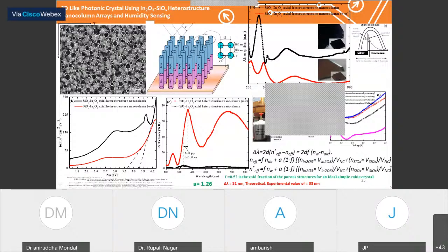We have seen that as the humidity has been enhanced inside the chamber, the current conduction of the devices has been enhanced. We have used some theoretical approach to determine the change of the band gap. We have seen the change of the band gap for both cases, theoretical and experimental, is nearly equal, and just 31 nanometer and 33 nanometer have been calculated, and the change of the conductivity has been measured for up to 99% humidity, changed from 55% humidity in the materials, and this has been due to the absorption of water at the junctions of the silver and the indium oxide.